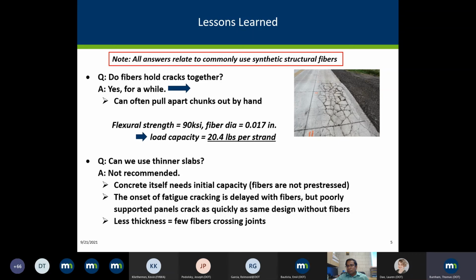At the same time, on many of these experiments that we've had, I've been able to go out and just pick up a chunk and pull it out by hand. So either the fiber slipped out of the matrix or the fiber does not have enough capacity. And I looked up, and an interesting fact, when you see the specifications from the manufacturer, they say this has a flexural strength of 90 KSI. It sounds very impressive. But that's based on the fact you'd have a 1-inch area of fiber all packed together. Well, we have individual fiber strands, which if you start doing the calculation, that's ultimately a load capacity of 20 pounds per strand. So now you can understand why somebody could walk over and pick up a chunk and pull it out of the matrix. So they really need to be quite concentrated for them to be able to survive some of the loadings that we're putting across the joints.